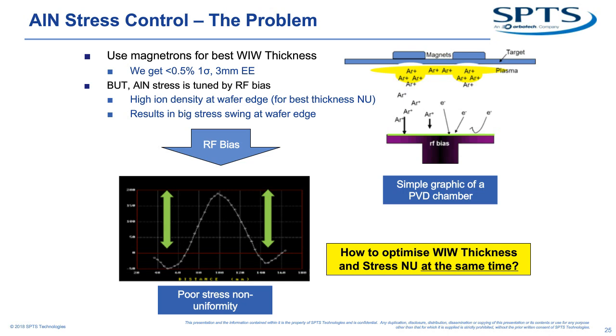And the arrival rate of the material, this sort of target and magnetron will give you good thickness uniformity. By working with the geometry of the chamber, the target to wafer spacing, you can get extremely good uniformity at the wafer. For us, we can get better than 0.5%, 1 sigma on an 8-inch wafer. But that is not the same as stress control.